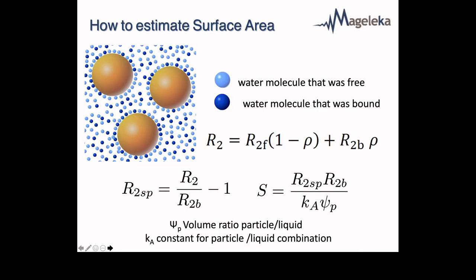Okay, so a little bit about how to estimate surface area. Now, you do need to calibrate this because the absolute values of the relaxation times for bulk water are known, but for the surface water, it's not known. So you have to basically have a handle on what that number is. But if you know that, we can encapsulate the unknown parameters in what we've called the Ka parameter.